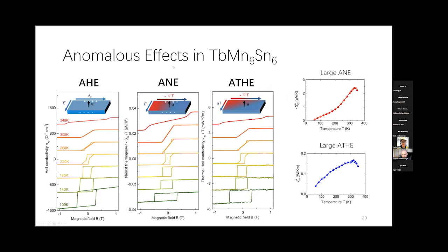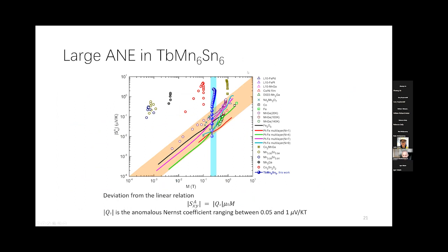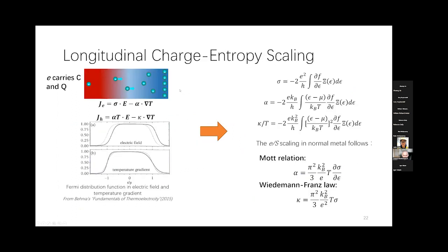That indicates we can do some measurements of the thermoelectric and anomalous thermal conductivity. And this plot shows 3 different anomalous effects in 166. And actually, we observe a strong anomalous Nernst effect and also a thermal Hall effect. The anomalous Nernst effect is pretty large at 1.6 microvolts per Kelvin at room temperature. And this is comparable with other topological magnets. Okay, so how to understand this